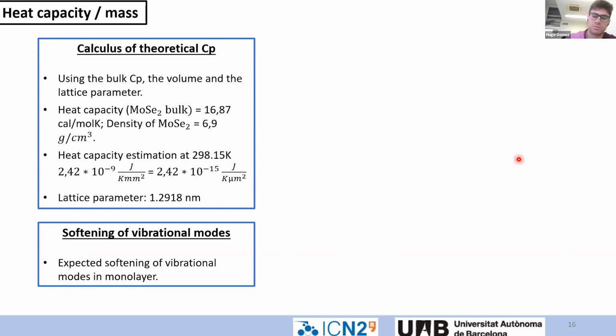We can also compare this with the calculation of the heat capacity of bulk molybdenum diselenide. We're using simply the bulk value reported in the literature, and using this heat capacity and the density of the material, we can estimate the heat capacity of a single monolayer by taking into account the lattice parameter of our material. Something that we expect, that we haven't done yet, is a softening of the vibrational modes in the monolayer, for example molybdenum diselenide, because these kinds of materials are not surrounded by neighbor layers as in the bulk material.